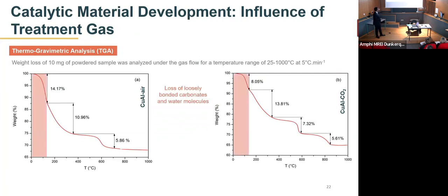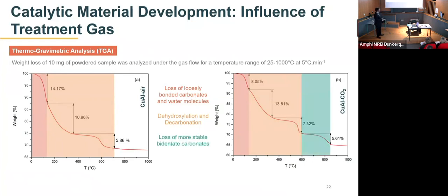So the first part of the weight loss is generally associated with the loosely bonded carbonates and water molecules. The second region is generally associated with the dehydroxylation and decarbonation process. So you have the hydroxide from the metal and the carbonate anions, which is present between the layers of the hydroxides, being removed during this temperature range. However, under the CO2 gas flow, we see an additional weight loss, which is generally associated with the loss of more stable bidentate carbonates.